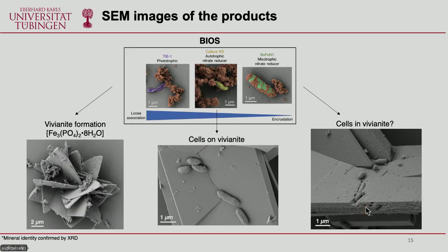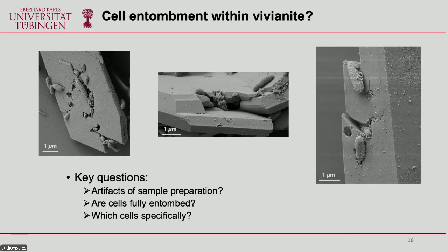But what's more interesting is that for this third type, where there's encrustation, we see evidence that there might actually be cells in the vivianite. We see more fractures, we see more holes. And this is not the only picture that we have. We have more under different conditions, under different time points. Here, for example, you see one cell that might be poking out right here, and here as well. Here you have a cell that is almost fully covered by vivianite, and here as well. So we see this kind of microfossil preservation, essentially, where the cells are being fully entombed within this vivianite.